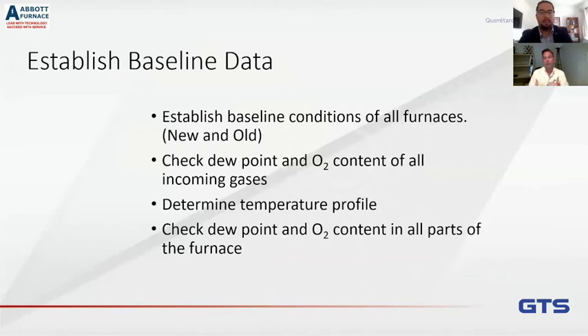Right. And I've seen this happen, especially if you're using tube trailers. They bring in a contaminated trailer and it ruins the atmosphere in the furnace. You'll see a high dew point in the furnace, but it's not because there's a problem in the furnace. You're bringing in contaminant. So always check your incoming gases.